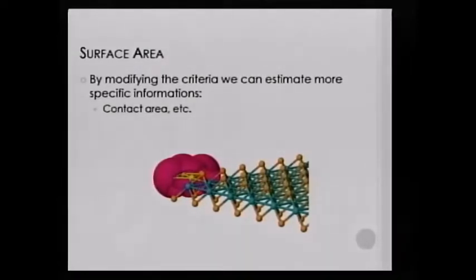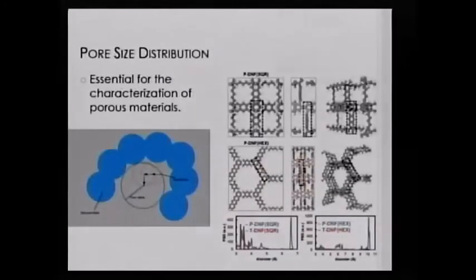But if you use a lot of probes per atom, you can get something more refined, for example. So, like I was saying before, this method is similar to Monte Carlo, but it also employs some optimization algorithms. You place, for example, a probe at a given point in a porous nanostructure, and you advance it using an optimization algorithm until the point where you can no longer move and increase the size of your probe. In this case, you have several steps, but you end up here and you can move no further.